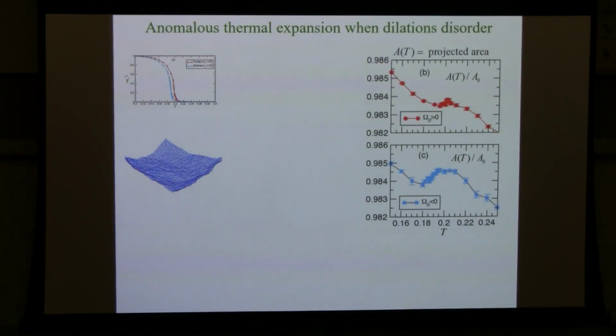And here's our little mechanical Ising antiferromagnet. And now you can plot the area as a function of temperature. And it's not monotonic. When these puckers are disordering, the system stops thermally shrinking, but it expands. Why does it expand? Why does the area go up and then down again? Eventually it goes down.